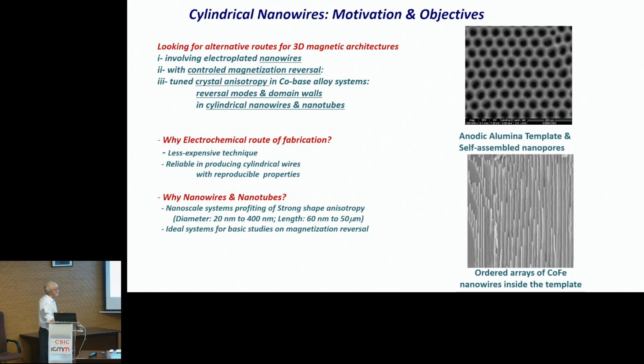So why, in the beginning, were we working with that technique? These nanowires are prepared by an electrochemical route. It is because it's very cheap, much cheaper compared to other techniques. And it is possible to obtain nanowires and nanotubes with very reproducible properties. So we have been working a number of years on these materials. As a summary, I can tell you that we can control the diameter of the nanowires roughly from 20 to 400 nanometers, and the length from around 60, 80 nanometers to 50 microns. So we can have a very high aspect ratio, length to diameter.